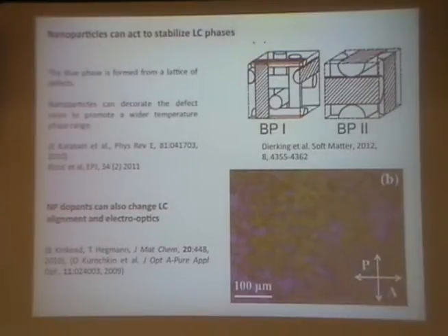One nice application of this has been in the blue phases. So blue phase has a very interesting structure. You have this lattice of defects throughout the material, it has this very chiral structure. And people have found that if we use some nanoparticles with the blue phase, they go to these defect cores and act to stabilize the phase, which is a really cool result. Because blue phase has nice applications for devices, however, typically the range of the blue phase has been really narrow, so it hasn't been an effective technology. But you know, this has been a nice advance using nanoparticles. And so this boils down to nanoparticles wanting to go to the defects.